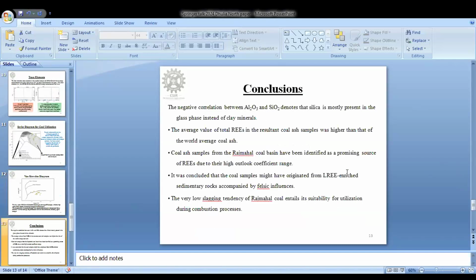And here is the conclusion. The negative correlation between aluminum oxide and silicon dioxide denoted that silica is mostly present in the glass phase instead of clay minerals. So either it's the glassy SiO2 phase, or it's in combination with aluminum as in clay minerals. Here it is primarily the glass phase. As I already mentioned, the average value of total REEs in the resultant coal ash samples was higher than that of the world average coal ash.